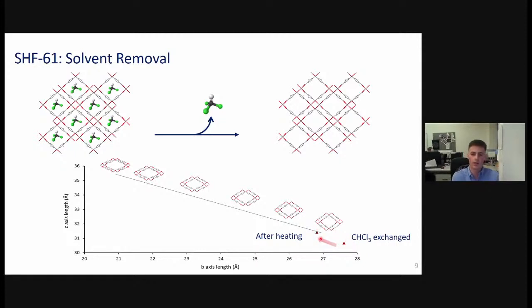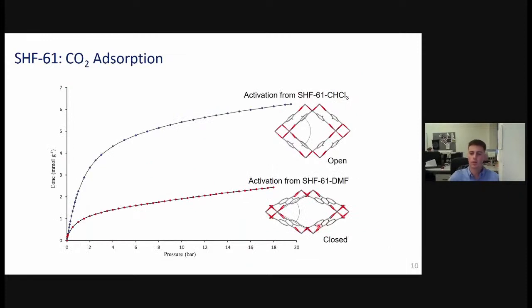So not only do we have this rather unusual continuous breathing mechanism, but we also have a framework which displays different behavioral responses dependent on the gas present within that pore. So we have some sort of solvent dependency. So going back to our gas absorption and why we have two different shaped isotherms, we now know that our starting point is two very different pore forms of the pore.